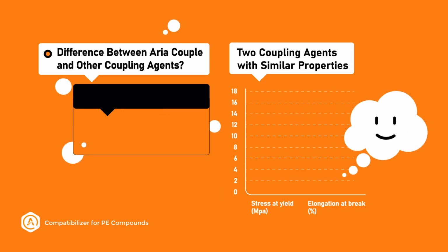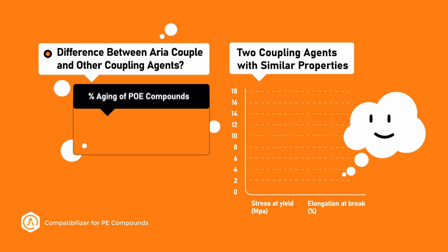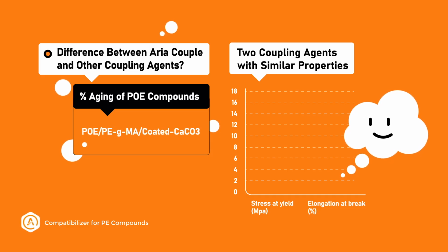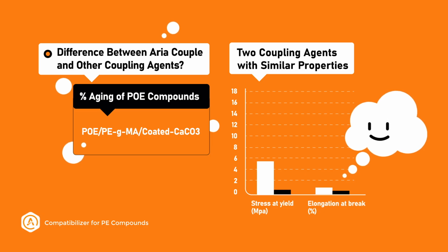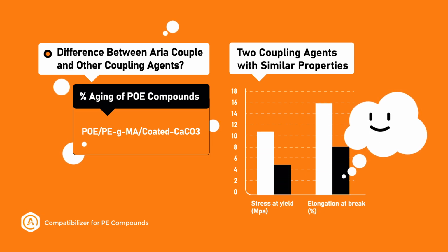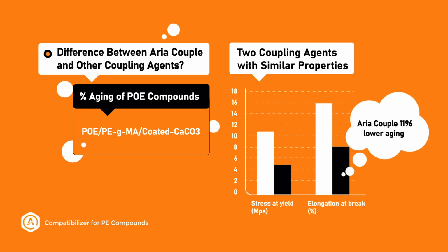Since changes in compound properties over a period of time are important in the use of polymers, the aging test has been done to evaluate coupling agents' performance. For this purpose, the introduced grades are used in polyolefin elastomer filled with coated calcium carbonate. To estimate aging of compound properties, mechanical properties were measured before and after exposure to temperature for a specific period of time. Consequently, the compound with Aria couple 1196 has lower aging and its properties change fewer at product shelf life.